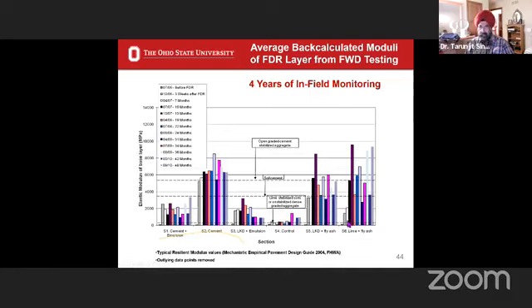modulus than this value. In fact, if you talk about rate of strength development, it continues up till about 7 months. This white line, I'm now going here, again, this is higher for S5. However, after about 7 months, if you see this black line, they are both similar. And they seem to cycle the same way.